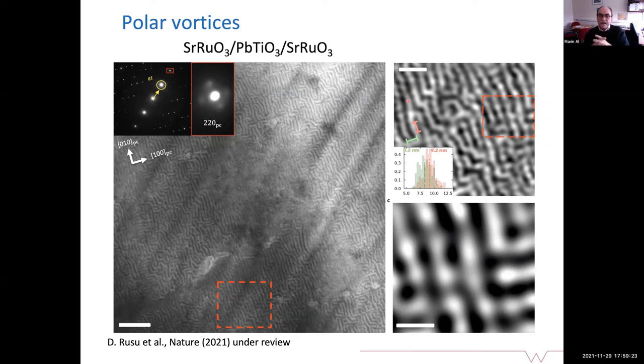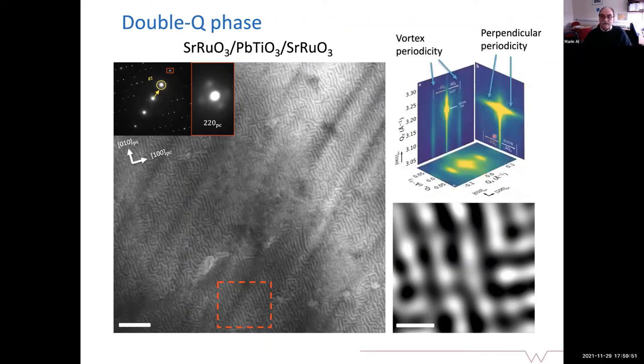That was surprising for us, and we were not so convinced about that. The only way to become very convinced is to do a macroscopic measurement, which is X-ray reciprocal space mapping. We did that at a synchrotron, and we see this scattering here, which is associated with the vortex periodicity. And we have another periodicity here, which is perpendicular to the vortex periodicity. So we twisted the sample by 90 degrees, and we measured along both of those periodicities.